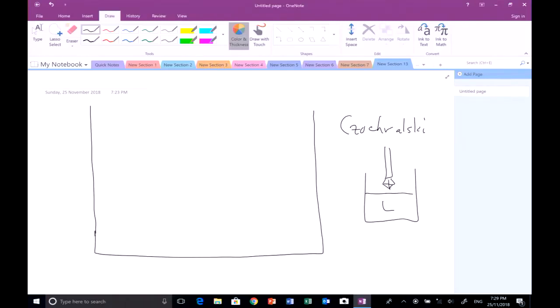Now, did I mention the early days of superconductors? We were growing crystals and physics and all that? Did I tell you that? Okay, well, this was the principle. The physicists didn't understand this. The superconductor was incongruently melting. Had it been congruently melting, everything would have been easy. They could have grown single crystals by the Czochralski method, piece of cake. But they couldn't do that. So for Czochralski, I need congruent melting. For incongruently melting, we have what's called flux growth.